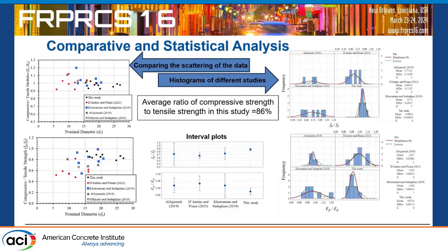Yours, okay, because in my experience, it plays a fundamental role, of course. If you increase the free length, you are completely changing the ratio between the compressive strength and the tensile strength. Also, did you try with different bars? Because in my experience, the type of bar, including the type of resin, the fiber volume fraction, and so on, play a very important role also in the setup, not only on the result.